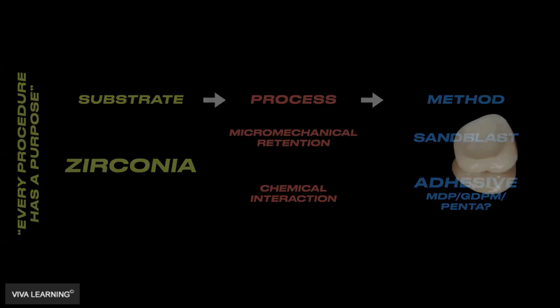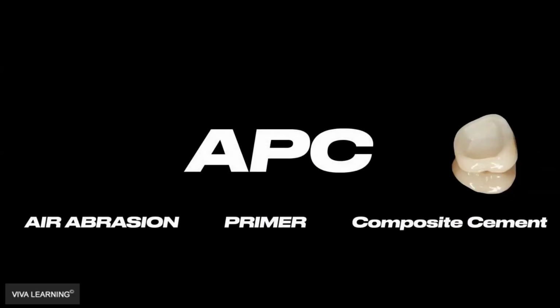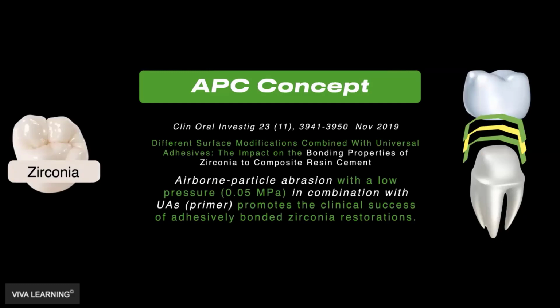All right. So let's talk about zirconia cementation. There's an acronym out there called APC for zirconia cementation. That stands for air abrasion, primer, composite cement. And this has been studied quite a bit. Here's a study that was done in 2019. Different surface modifications combined with universal adhesives and the impact on bonding properties of zirconia to composite resin cement. Basically, they found that airborne particle abrasion with low pressure, right, in combination with universal adhesive primers promotes clinical success of adhesively bonded zirconia restorations.